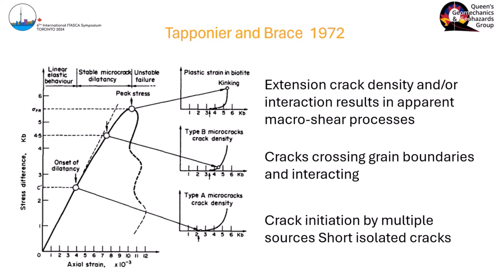In the same paper, they identified, I don't know if this is the first time, it's the first time I found, they identified this onset of dilatancy in a test, confined or unconfined. At some point, the linear axial stress strain behavior starts to go nonlinear. And then, of course, you have failure in post peak, and they describe these in this way. So you have initiation from multiple sources, short isolated cracks. Those cracks cross grain boundaries, start to interact, and then finally it becomes so much that you have a macroscopic shear process. And so this, a long time ago, with physical reasoning, was the basis.